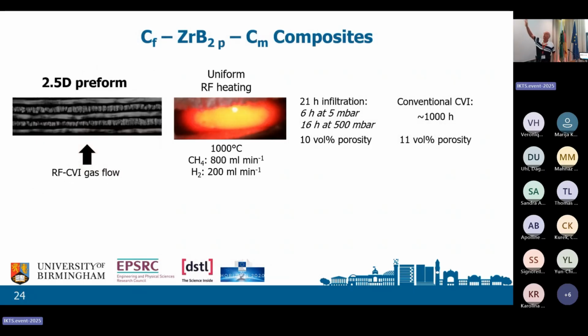So this is just one example. Carbon fiber, zirconium diboride, carbon as your matrix, 2.5D preform, gas flow going through. There's the part being heated. You can see it's hottest in the middle and coolest on the outside. 21 hours later, you've got something which is 10, 11% porous. Now with CVI, you will always end up with about 10% porosity. That's the limitation of CVI. You won't get more than 90, 91% dense. But there's no difference between the microwave and the RF and the conventional. They're both very, very similar. And the properties, you wouldn't be able to tell which route had been used.